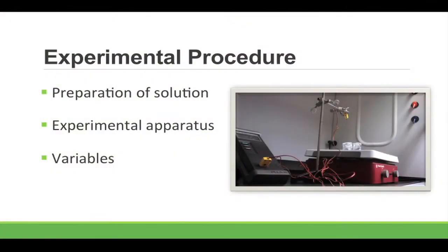So now moving on to our own experimental procedure. To prepare solutions, crystals of urea and zinc nitrate hexahydrate were mixed with distilled water in Pyrex beakers. Two copper wires were placed in each beaker in order to serve as the substrate on which the nanostructures could grow. And aluminum foil was used to cover the beakers in order to prevent water loss during the heating process.